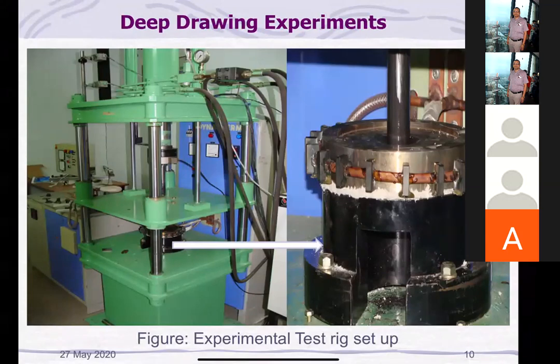So now this is the experimental setup. We have a high temperature forming setup. It was basically the first setup that we developed at GRIT in the year 2008. But now most of our work we do on the BIS system. The problem with the BIS system is that loading and unloading consumes a lot of time. So when we have to do preliminary studies up to 400 degrees centigrade, we still use this machine.